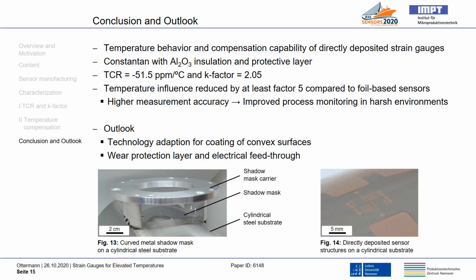The first result of a first sputtering process is illustrated in figure 14. Here you can only see the sensor structures in X direction. The reason for this is the fact that the sensor design has to be divided into 2 shadow masks for the X and Y direction. Otherwise, some parts of the metal shadow mask would not be in direct contact with the substrate because of its curvature. The alignment of 2 shadow masks to each other is quite important to generate the original sensor layout again.